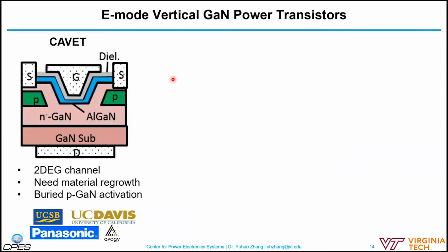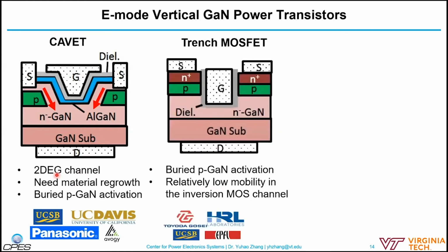Okay, now I'm going to introduce several vertical GaN power transistors. The first one is called the CAVET, current aperture vertical electron transistor. This transistor still utilizes a two-dimensional electron gas channel. You see the aluminum gallium nitride and gallium nitride, so there is a two-dimensional electron gas at the side walls. The current is confined by the barrier, the p-type layer, to flow in a very narrow region to enable the gate control. So it still utilizes the two-dimensional electron gas channel. And the second one is very similar to the silicon carbide and silicon counterparts, called the power MOSFET, especially the trench MOSFET. There is a trench gate, and the current flows in an inversion-type MOS channel.